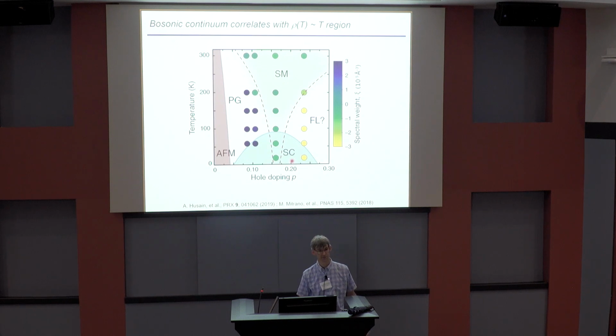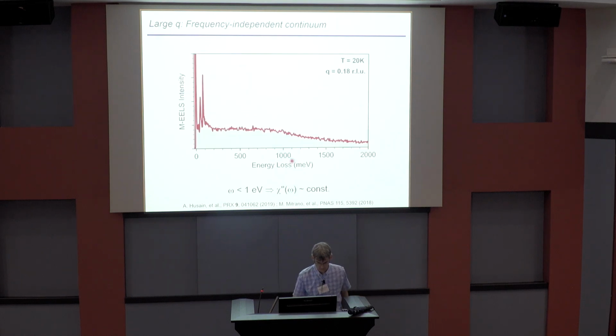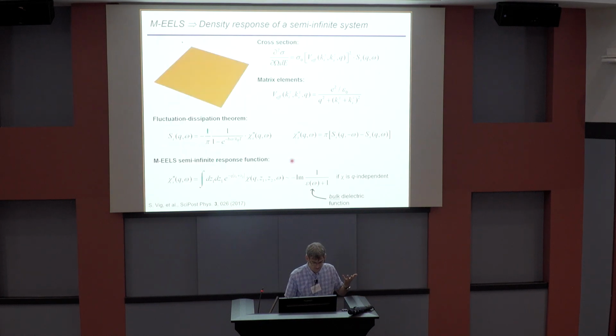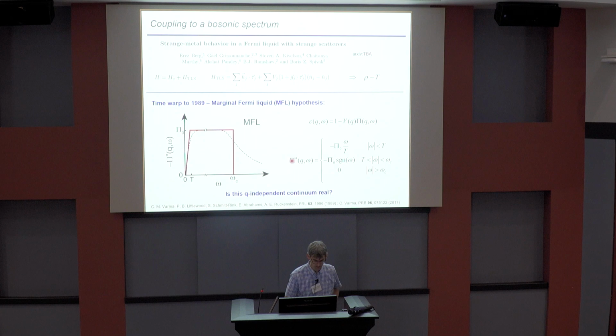Okay, so what I really wanted to do is show you the low energy data. So if you zip back, sorry, I just made my talk last night and this morning, but at low energy, this thing is supposed to be frequency dependent. And the slope of this is supposed to be given by 1 over T, and that's crucial because that's the part of this that gives you the T-linear resistivity.